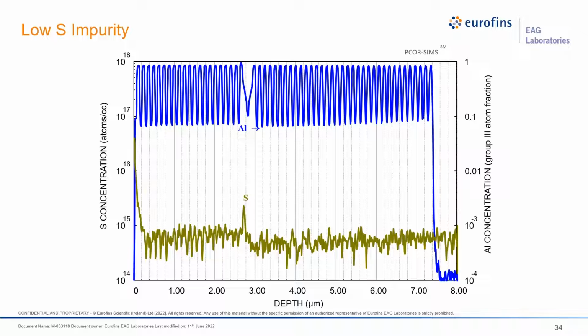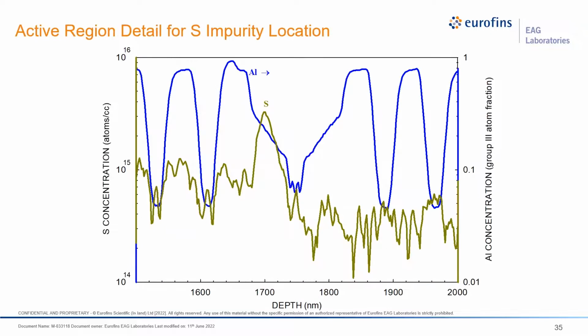Occasionally, VCSELs contain sulfur impurities, which are believed to affect performance. The level of sulfur is typically higher in the PDBRs than in the NDBRs. The peak in the upper graded AlGaAs cladding layer is easier to spot in the higher resolution analysis of the active layer in the next slide. This slide shows how the sulfur contamination peak is actually located in the middle of the grade of the aluminum in the P-type cladding layer.